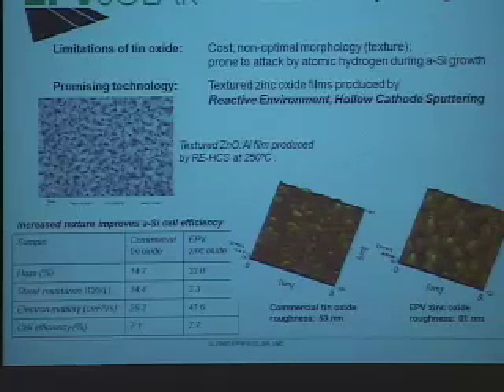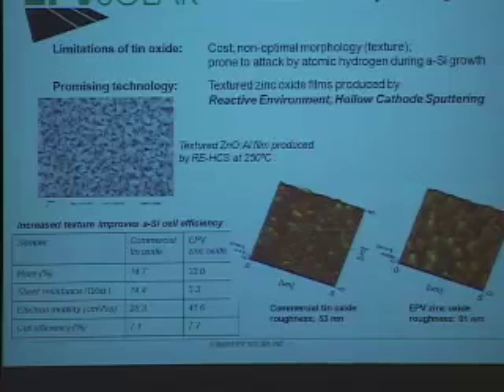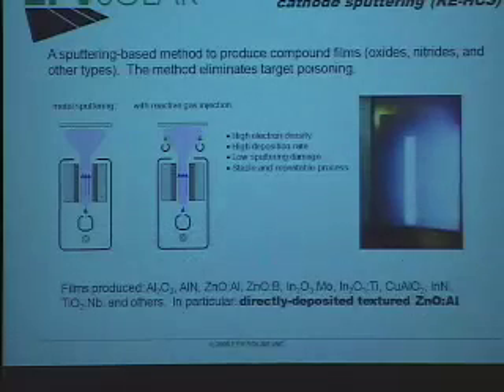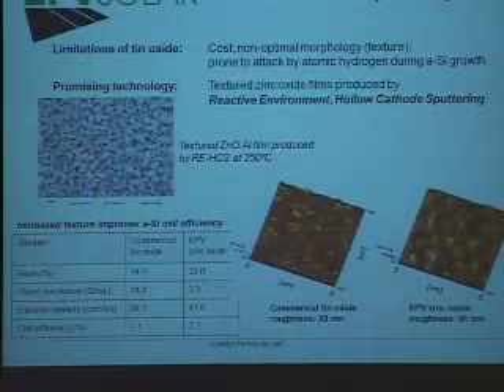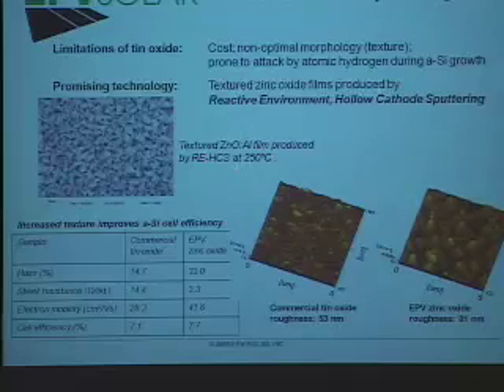Now, you also need the transparent conductor on the front. You need an electrode that is the front contact, which has to be conducting, but it has to be transparent at the same time, and it also has to be textured to induce light trapping in the device. So at the moment we use commercially made tin oxide, but it has these drawbacks. And we've developed a new route for making textured zinc oxide by a method we call reactive environment hollow cathode sputtering. I'll show you what that is in a minute.